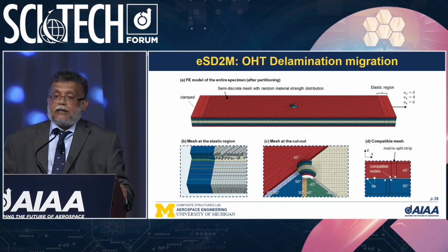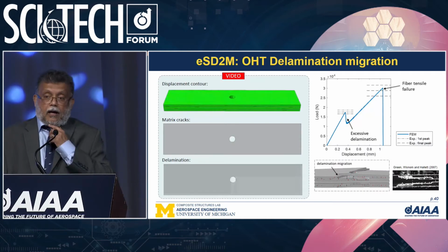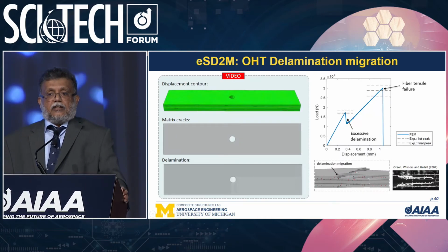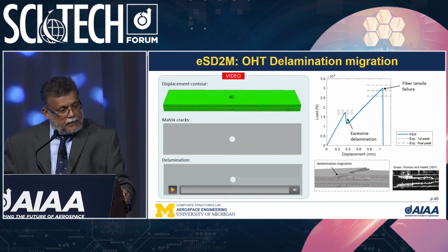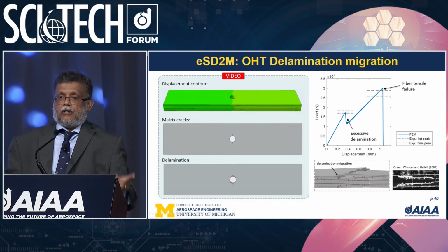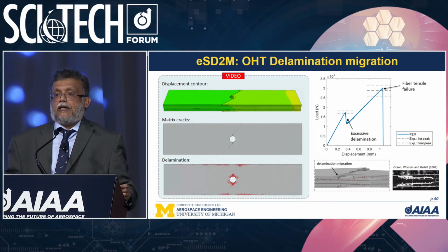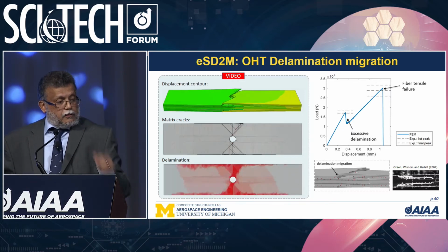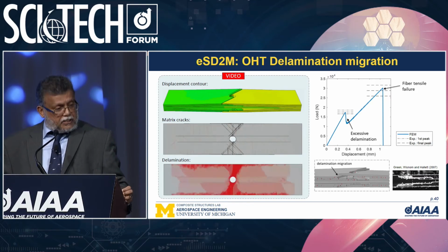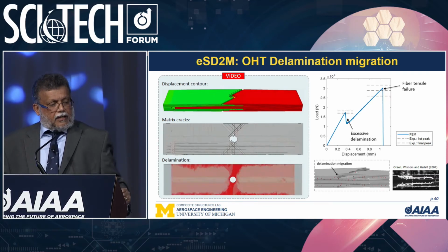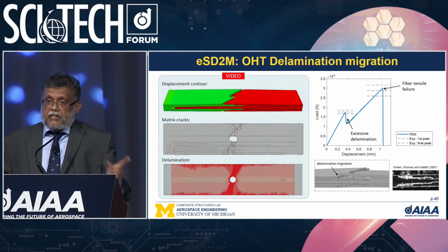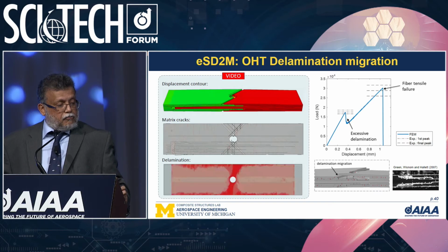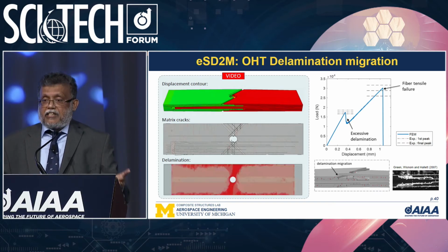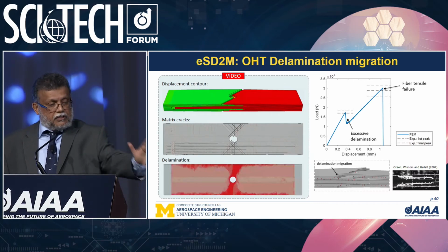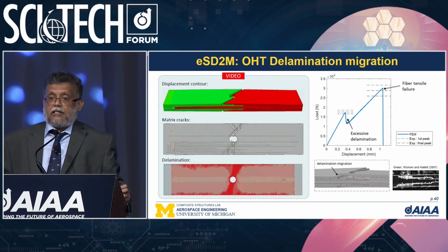Showing you the mesh and the details of the layup. What's interesting about this particular test is that the load deflection curve is non-monotonic. It has a first peak, the load drops, stabilizes, and then increases again until you get complete failure. The movies there show our predictions, and on the right hand side we show the actual pictures published by Green, Wisnom and Hallett, which show the migration pattern and the way the delaminations migrate along with the matrix cracks, very accurately captured by the ESD2M model.